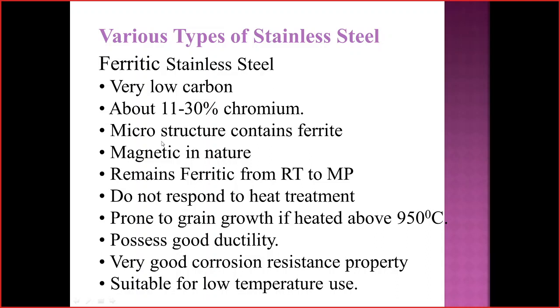The microstructure contains ferrite, and it is magnetic in nature because of low carbon. Even though it is a steel, it will be attracted by a magnet because of the ferritic structure. The steel remains ferritic from room temperature to melting point, does not respond to heat treatment, and is prone to grain growth if heated above 950 degrees centigrade.